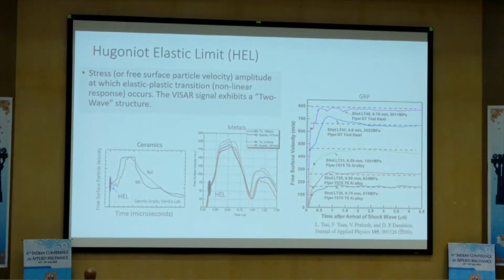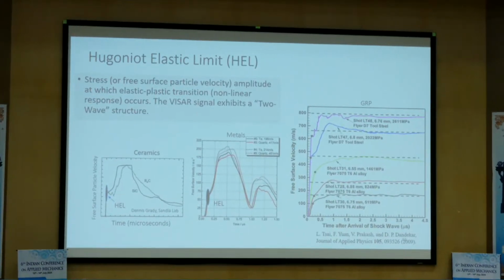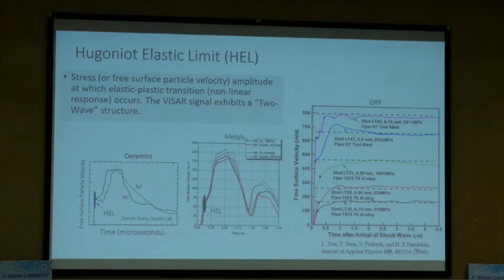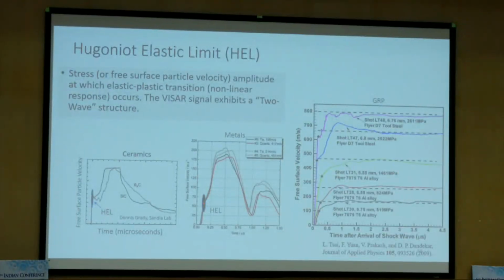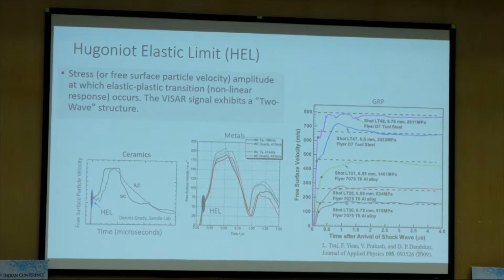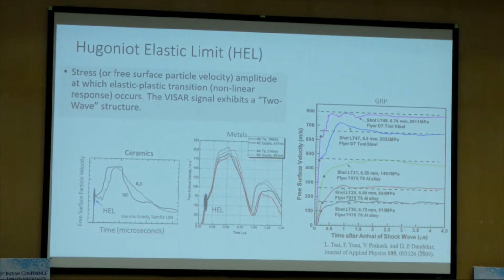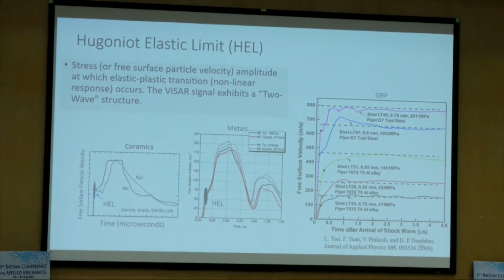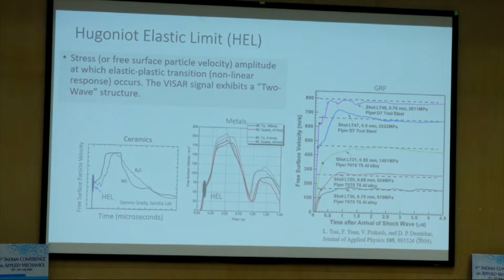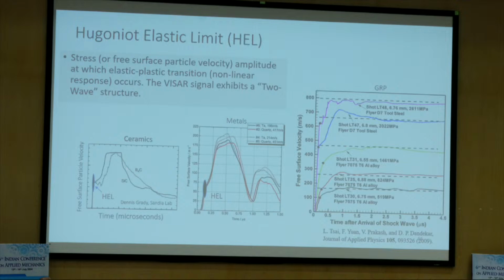Now metals, same thing, elastic, and then you have Hugoniot elastic limit. That is the limit of elastic deformation, it ceases, inelastic deformation occurs. In metal, it is plasticity, and in ceramic, it is micro cracking and dislocations, twins, and you see the elastic and then elastic plastic transition. And of course, this is spallation. This spallation is a tensile failure in metal, and you won't see it in ceramic. See that? It doesn't go up. It comes down and goes up. That is spall signal. In the ceramic, there is no spall signal because tensile strength becomes zero.